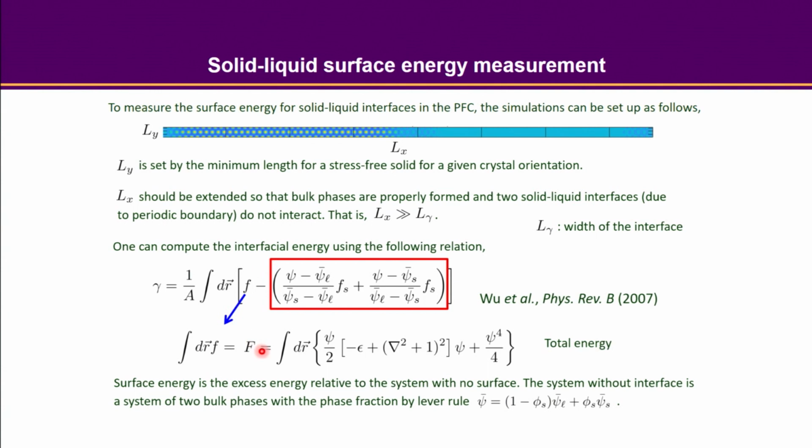The total energy that you can calculate with this phase field, and the rest of that part is the one without interface. And this thing you don't have to do, you don't have to carry out the integral, because although I'm writing in this form, you can see that you have a solid-liquid coexistent density, and also the solid free energy density and the liquid. There's a typo, and there should be a solid and liquid. So here basically is, according to the lever rule, what the energy is.